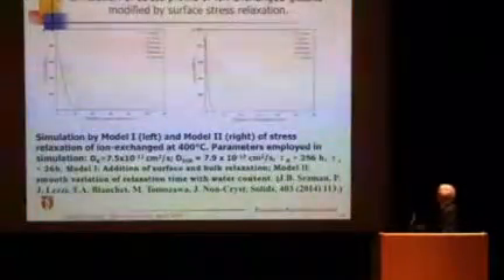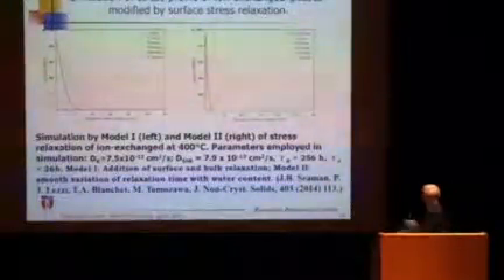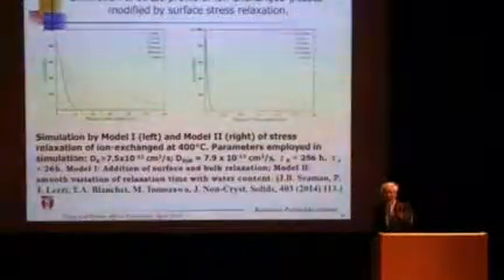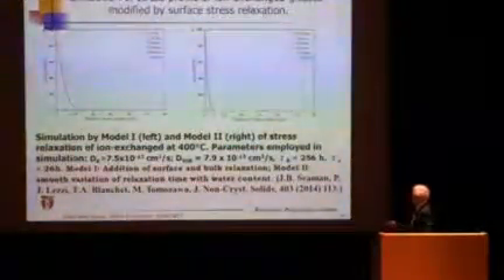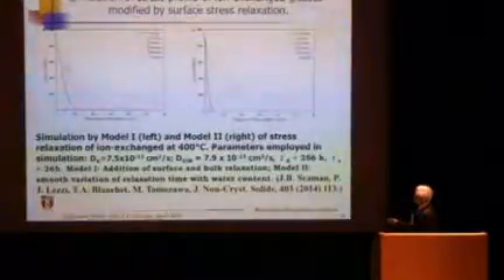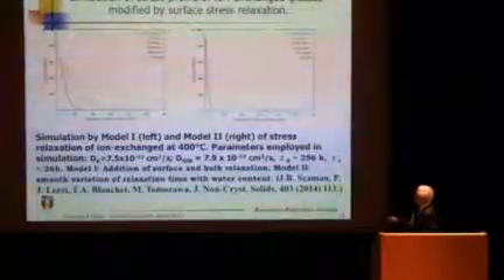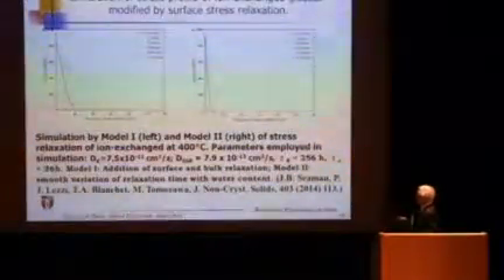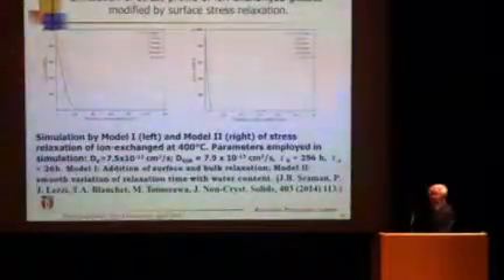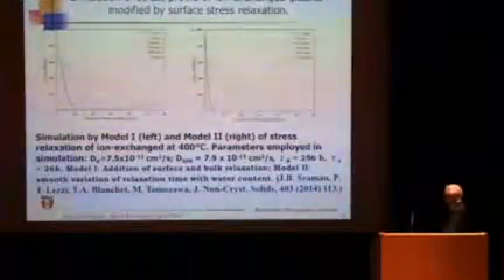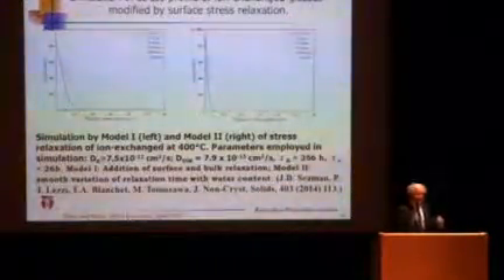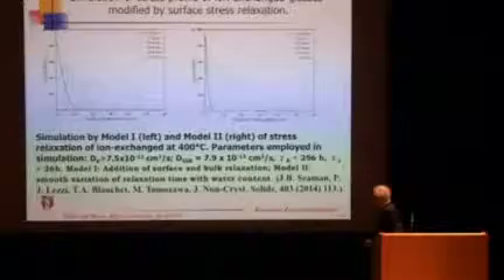And using this idea, we simulated, incorporating this surface stress relaxation coming by diffusion process, we modeled other people's experiment, and with time we could more or less show the position of the peak is shifting inward and coming down. There are two different mathematical models used, and both capture the essential features of experimental observation. So I believe we solved this mystery of why the surface compression of ion exchange glass goes down. And this was published this year in Journal of Non-Crystalline Solids.